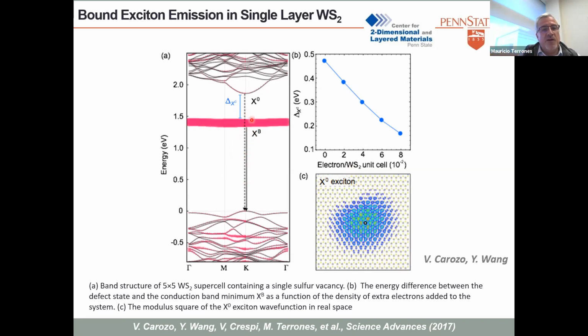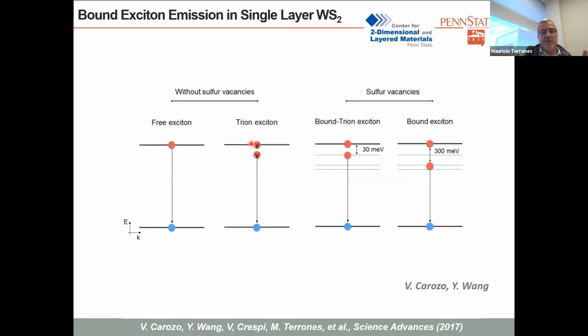Here we have one sulfur vacancy, and what happens is that this vacancy induces a mid-gap state, right? So this is the valence band, the conduction band, and you have the mid-gap state introduced by the vacancy. This energy is related to these 300 milli-electron volts. So in this sample, what could be happening is that on the outside of the triangle we have a larger concentration of sulfur vacancies, and that's why we see this beautiful pattern.